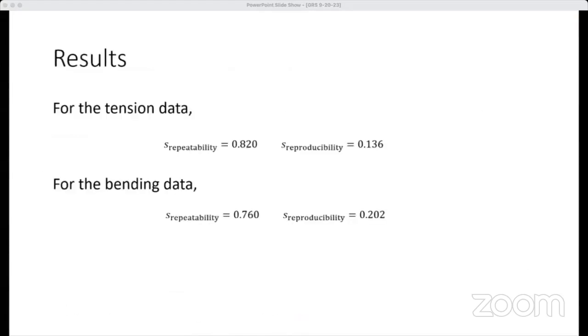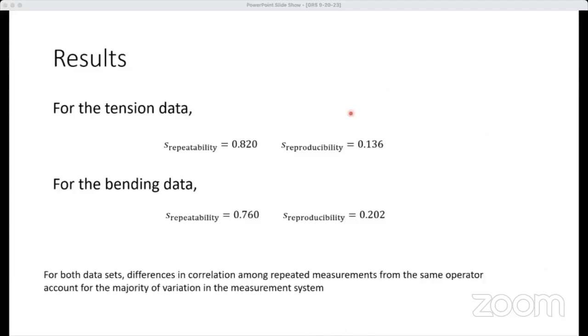So for the tension data, this value for repeatability is around 0.8, whereas for reproducibility, it's around 0.14. And while these two values are not true proportions, they don't add up to 1, what it's telling us roughly is that around 80% of the total variation in the measurement process is due to this repeatability part, meaning the differences in measurements of the same sample made by the same operator at a different time. And since the reproducibility aspect is so low, it's telling us that measurements of the same sample made by different operators on average will tend to be quite similar to one another.